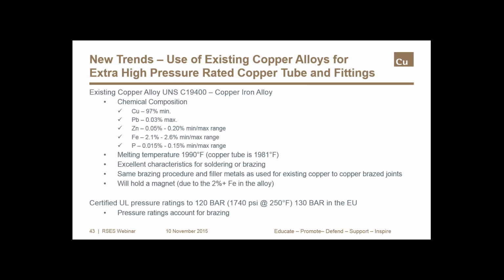Also note that the pressure rating does cover brazing and its annealing effect. So if you plan to braze this tube, you don't have to reduce the pressure rating by some 29%, like you would for conventional HVACR tube. This alloy has excellent brazing properties, and it allows the exact same brazing process to be used that's used for HVACR tube. But specific braze alloys are recommended for this extra high pressure tube.